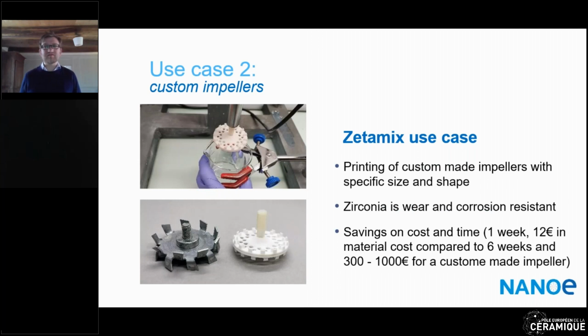So we decided to replace a stainless steel impeller blade by a ceramic one, which allowed us to modify a bit the shape and the size of the impeller, and to make it in zirconia. Zirconia is a very high wear and corrosion-resistant material, and that allows us to stir very corrosive, very aggressive suspension without any risk of pollution.